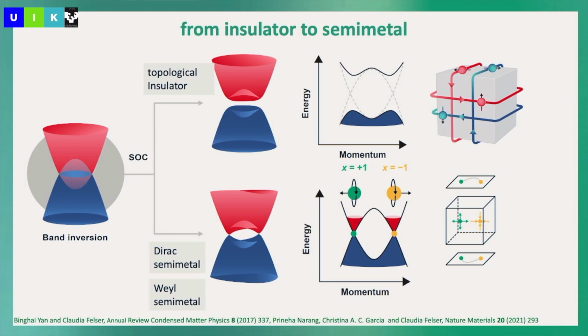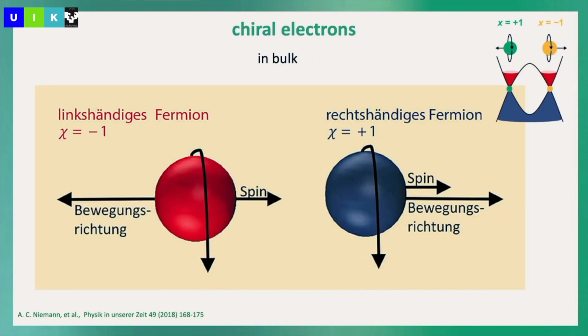So we have here in our crystal these different crossing points in the bulk electronic structure, which have different signs of the Berry curvature, and they look like a source and a sink of a Berry curvature. And then the surface state, which was predicted here, is this projection of this bulk electronic structure, this Fermi arc, which connects the projection of these 2 points on the surface. And I think this is a very interesting class of material.